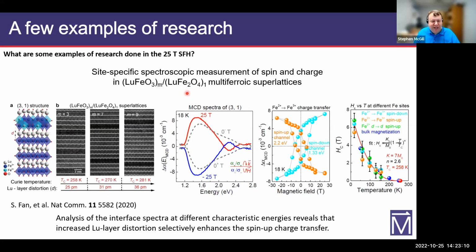So by doing a measurement called magnetic circular dichroism, we can look at the hysteresis loops in the material. And because we can do this for different wavelengths of light, we can get an idea of how the interface magnetism is changing in an energy selective way. So for example, one of the things that was discovered here is that for different combinations of layers in the superlattice, the spin-up charge channel for the Fe2+ to Fe3+ transition, which was at about 2.2 electron volts, got larger. And so this explained what was going on in terms of the enhanced magnetization in this system, because the MCD signal was proportional to the magnetic moment in the material.